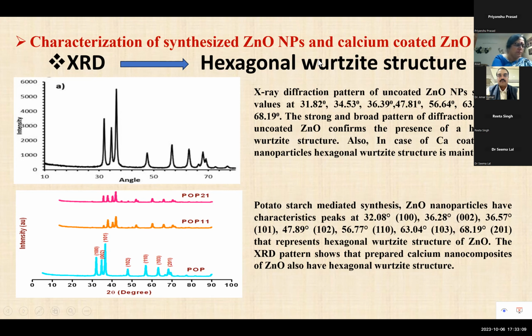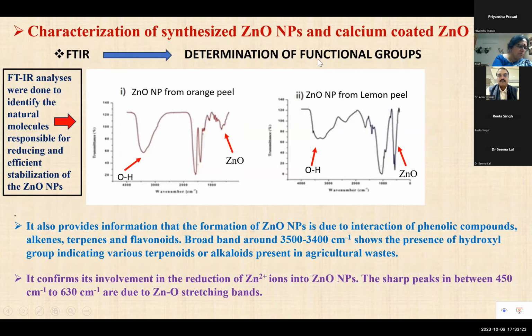The XRD pattern also shows that the prepared calcium nanocomposites of zinc oxide nanoparticles also have a hexagonal wurtzite structure. And the next is the characterization through FTIR, where the FTIR analysis was done to identify the natural molecules responsible for the reduction and efficient stabilization of the zinc oxide nanoparticles. It also provides information that the formation of zinc oxide nanoparticles is due to interaction of phenolic compounds, alkenes, terpenes, and flavonoids.